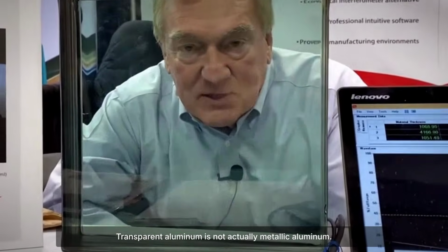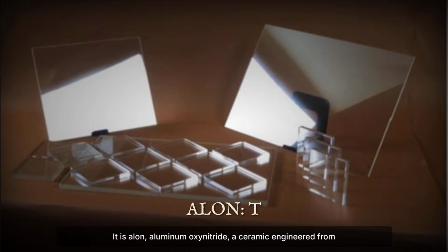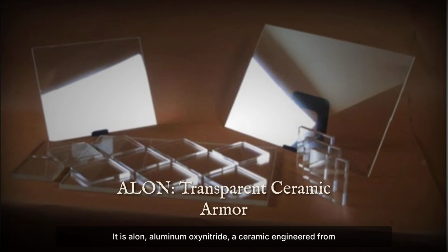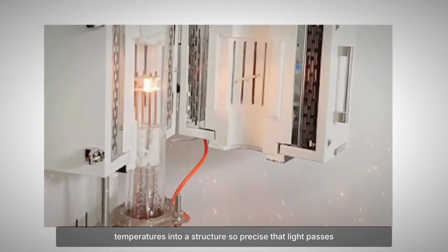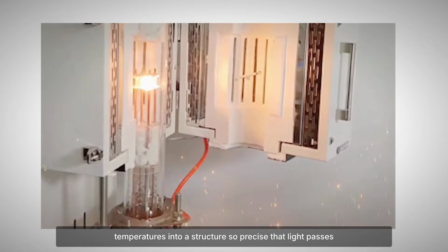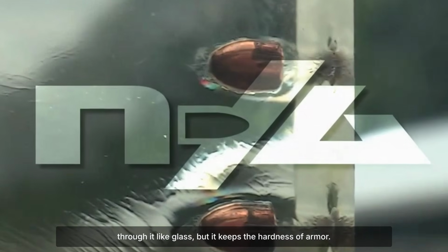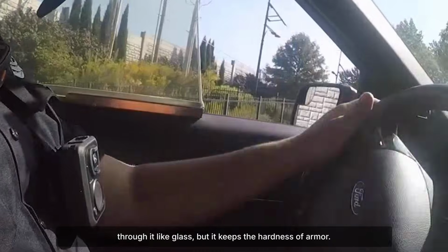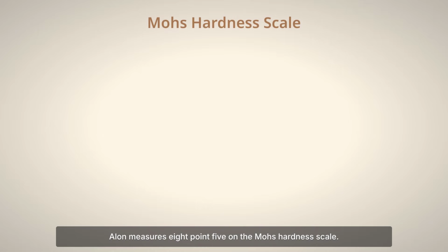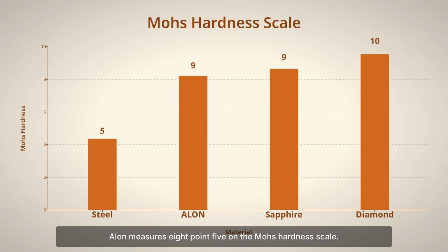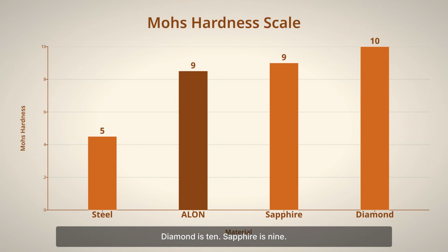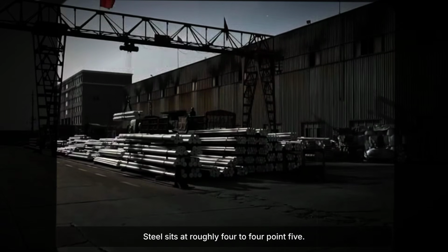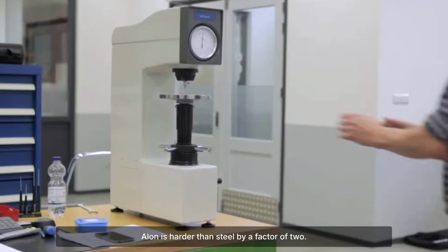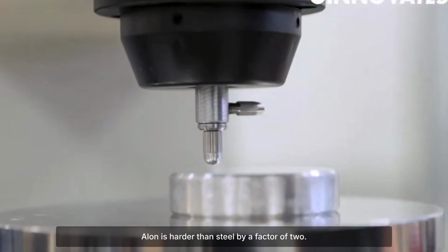Transparent aluminum is not actually metallic aluminum, it is Alon, aluminum oxynitride, a ceramic engineered from aluminum, oxygen and nitrogen, sintered at extreme temperatures into a structure so precise that light passes through it like glass, but it keeps the hardness of armor. Alon measures 8.5 on the Mohs hardness scale. Diamond is 10, sapphire is 9. Steel sits at roughly 4 to 4.5. Alon is harder than steel by a factor of 2.